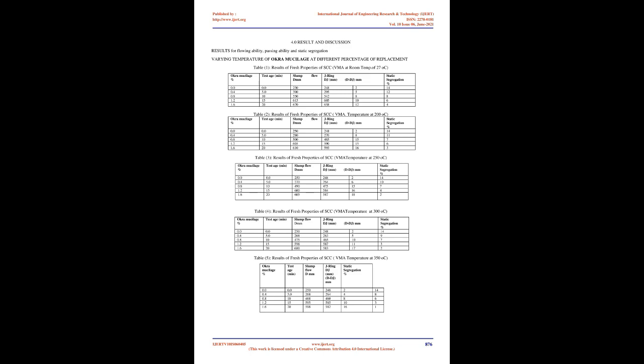After a short rest, no more than 30 seconds, for cleaning and checking the moist state of the test surface, the cone was lifted perpendicular to the base plate in a single movement, in such a manner that the concrete is allowed to flow out freely without obstruction from the cone, and the stopwatch was started the moment the cone loses contact with the base plate. The stopwatch was stopped when the front of the concrete first touches the circle of diameter 500 mm. The stopwatch reading was recorded as the T50 value.